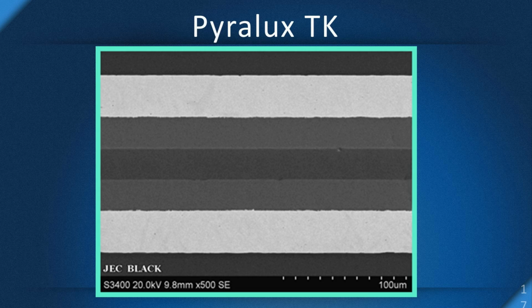So in this case, the Kapton is performing the same function as fiberglass. If you made a board out of pure Teflon without any filler or reinforcement, it would be very dimensionally unstable. It's very soft. Teflon actually cold flows at room temperature. So that's why all these different materials, 3003 and the like, have different things in them to help with the XY stability. In this case, DuPont has made what we call a laminar composite, where they have a layer of Kapton in the middle that provides the XY stability, but the Teflon provides the really low loss characteristics.